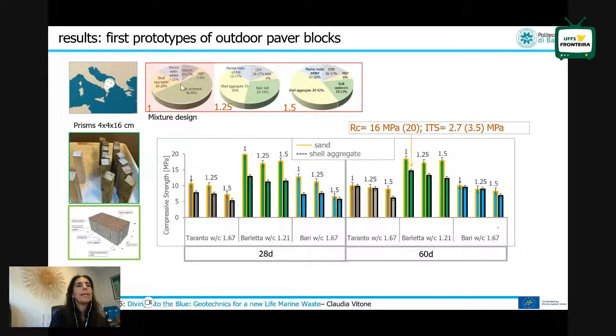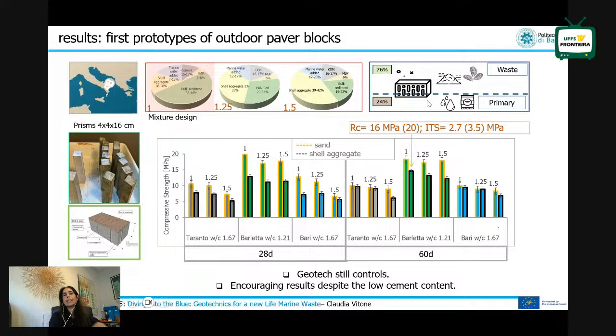is characterized by a mix design that is essentially made up of 40% of bulk sediment, then 10% more or less of marine water, shell aggregate. So all this is secondary material. The shell powder is secondary material. Only the cement is 16-17% in the brick. But we are already having very good results because the compression strength is 16 megapascal against the 20 that is suggested by the codes, the standards, and the indirect tensile strength is 2.7 against the 3.5 of the standards. So we have in our bricks just 24% maximum of primary material against the 76% that is waste.